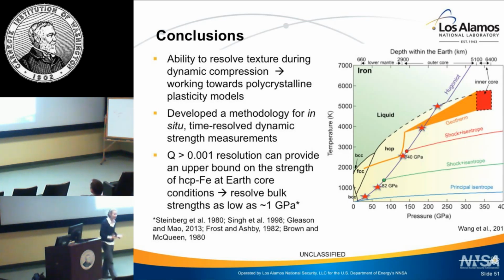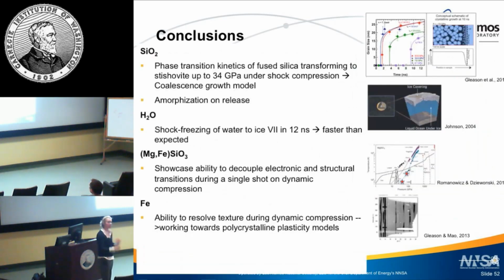looking at time-resolved phase transition kinetics in materials that are important, not just for our planet, but other planets in general. We looked at fused silica transforming to stishovite, finding that we have this aggregation of these nanocrystalline particles that then grow, and then an amorphization or reversion to an amorphous, perhaps diaplectic glass on release, okay? The water shows shock freezing into ice VII, okay? And it's very fast, only say several nanoseconds to nucleate and grow, perhaps these elongated crystallites of ice VII.